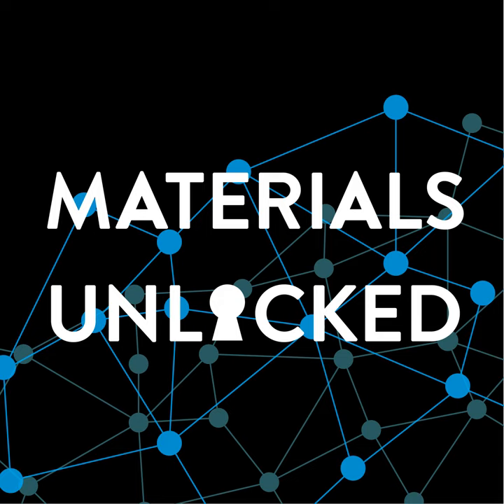So we're looking at structural materials, but we recognize that there are conventional structural materials which are versatile. In our case, we're looking at steels. Conventional steels have some quite severe limitations for us in a fusion reactor. For instance, radioactivity is one of them. An interesting point with fusion reactors is that because the neutron energies are so much higher than you get with a fission plant, we need to be concerned with how active structural materials become. There's no spent fuel with a fusion reactor, so you don't have to worry about radioactive fuel and storing that for tens of thousands of years afterwards, as you do with a fission plant.